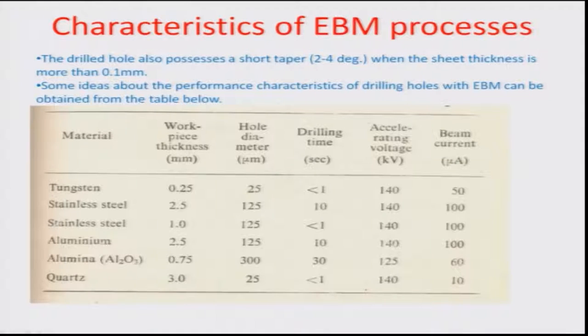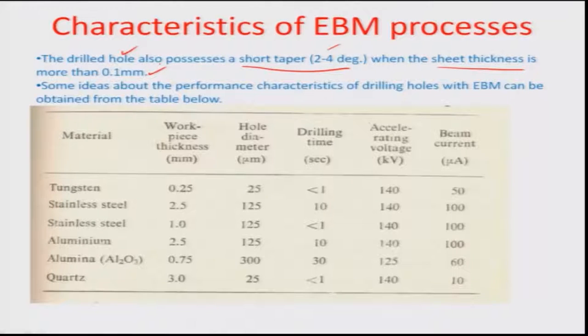So the drilled hole will also possess a short taper in this particular case, particularly because the beam also narrows down, and there is something like a beam focus which is hit upon somewhere at the depth up to which the cutting has to happen. And so for doing this, you always have this tendency of about 2 to 4 degree taper whenever you are using a sheet thickness more than about 100 microns. Okay, so anywhere above 100 microns, you will definitely get a taper in the hole that you are trying to drill.